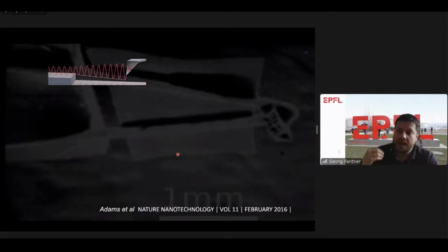And what that means now for AFM imaging is that if we are oscillating in tapping mode along, and then we're getting to a change in topography, the cantilever initially does not actually change too much in the amplitude. That's because this change in boundary condition, this change in topography, only will be detected once the cantilever has obtained enough additional energy to reach the new steady state amplitude. And that time during which we're having this ring up, we are blind to the surface. So this time determines how quickly we can scan and how quickly we can take our image.